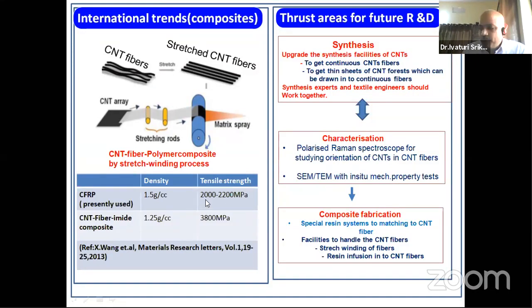So in terms of tensile strength, there is a definite possibility of improving tensile strength provided you use exclusively continuous CNT fibers only. What we have seen so far, most of the research is on dispersed CNT fibers. CNT fibers are not continuous like this. Pieces of CNT fibers are added as a powder into the resin system along with the conventional carbon fibers. That will never work. If you make continuous CNT fibers, realize fabrics with that, and then make a composite, then you can get it. This was already reported in 2013. People are making composites with strength of around 4,000 MPa, against 2,000 MPa strength of present-day carbon fiber reinforced composite.